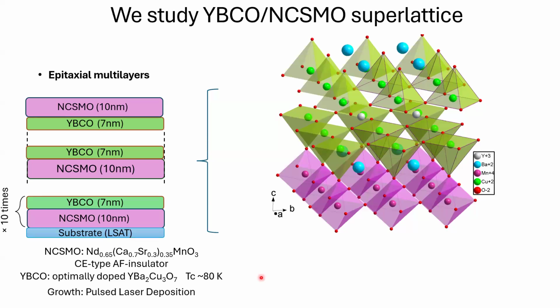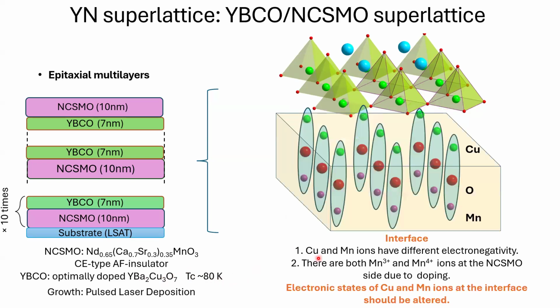We study a YBCO manganite, cuprate-manganite superlattice, which is created by pulsed laser deposition. With special doping, the manganite is in an insulating state, of CE type, an antiferromagnetic insulator. Whereas YBCO is present as an optimally doped compound, which has a Tc around 80 K. And we will study what is going on at the interface. What do we expect in this case?